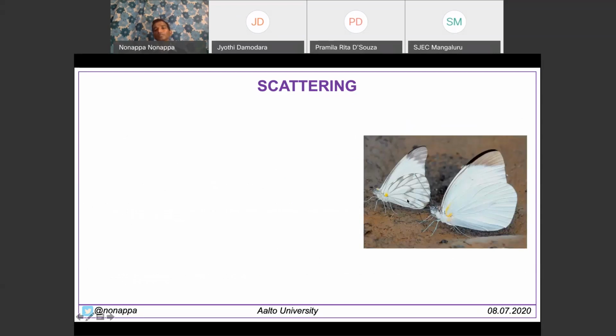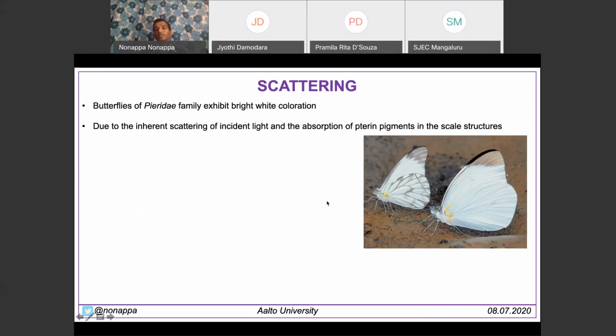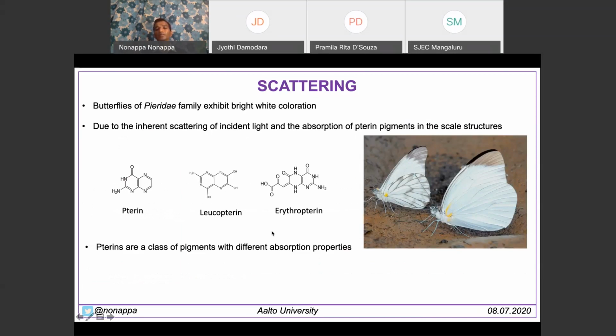One of the special examples here is butterflies. You can see that they have nice white, bright coloration. And this is because of the pigments that they have. These pigments are called pterines, which are different chemical components that result in a number of pigments that selectively absorb certain light. For example, leucopterin can absorb in the UV wavelength. And this one, because of the higher conjugation, more functional groups, can absorb at 500 nanometer.